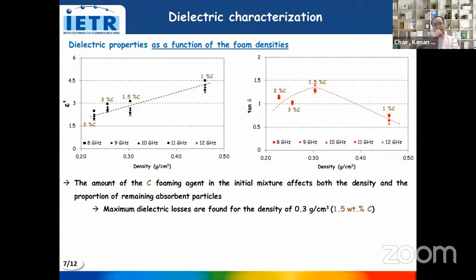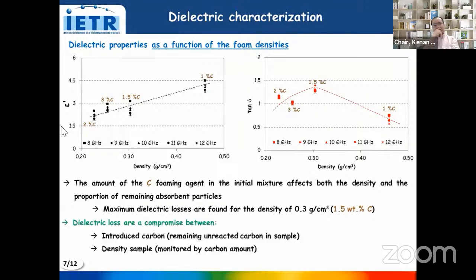Here are presented the dielectric properties of the same samples as a function of the foam densities. The real permittivity presents a linear evolution as a function of the density independently of the carbon percentage, but the losses increase with density before decreasing for the last sample. This result confirms that the dielectric losses are a compromise between introduced carbon in the mixture and the unreacted carbon remaining in the final foam sample, but also the density of the sample, which is also monitored by the carbon percentage. The chosen composition for the prototype was 1.5% of carbon.